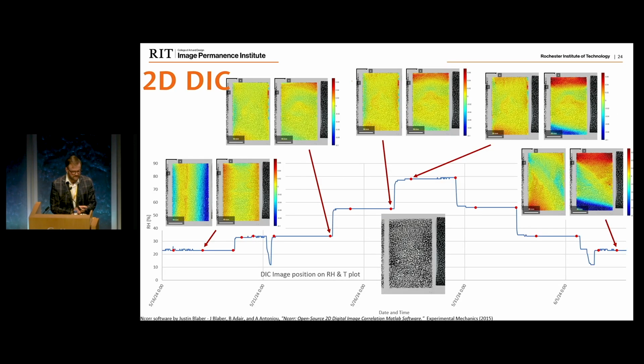So what it showed us is that, first of all, when you look at the images that are scaled to the global maximum and minimum, so the color scales here are the maximum and minimum for the entire test, the left image is the x-axis strain, the right image is the y-axis strain. So what you can see here is kind of the same situation that you have seen. This is an example that contains a small cross that covers 8% of the surface area of the sample, a number taken from one of the animation cells that we've seen. And what you see here is that at the end, the sample has not returned. It has curled more after drying than when it was relaxing during humidification.